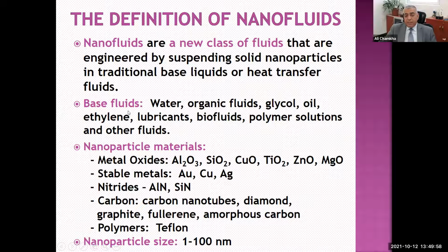Typical base fluids are water, organic fluids, glycol, oil, ethylene, lubricants, biofluids, etc. Typical nanoparticles that are being used: metallic oxides like alumina, silica, copper oxide, etc. Stable metals like gold, copper, and silver. Nitrides could be aluminum nitride, silicon nitride, carbon nanotubes, diamond, etc. Nanoparticle size, as we said, between 1 and 100 nanometers.